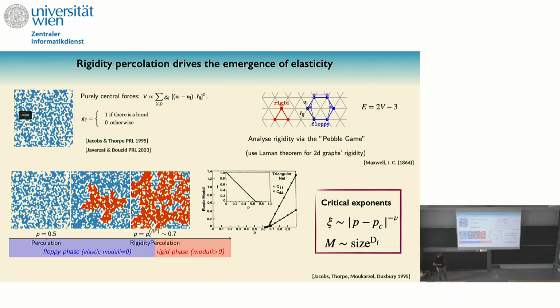A critical exponent related to the correlation length, nu, but also to the growth of the size of your cluster, which gives you the fractal dimension. There are hyperscaling relations and so on and so forth. But I want you to pay attention to this exponent nu, because this exponent turns out to be very important in order to predict the emergence of elasticity, but also the linear elastic properties of a system. Just by knowing this exponent, you would be able to trace back what the rheological property of the system would be.